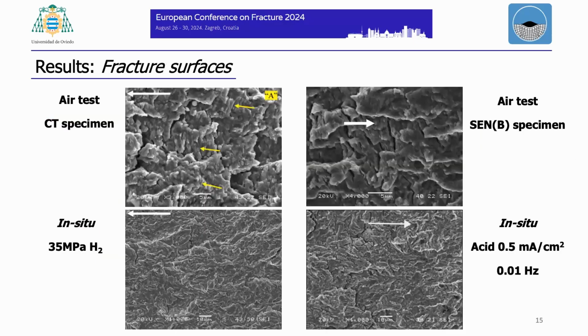Also, we observe the fracture surfaces for the air test and for the in situ test that are similar. On the left, we have the CT specimen. In the air test, in both, we were able to see the striation lines typical of this kind of test. And in the in situ test, with the condition that is similar to the gas test, the fracture surface is exactly the same.